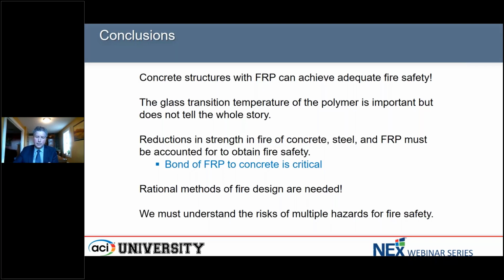Certainly the glass transition temperature of the polymer is important, but it doesn't tell the whole story about what's going on with the material. And so we will get reductions in strength of all the materials in fire, but the one that's particularly important, and this is for FRP reinforced concrete structures in particular, is the bond of the FRP to the concrete. And that is critical to make certain that you can have some end anchorage zones that are in a cooler region where you can get a better bond and anchorage of the bar.